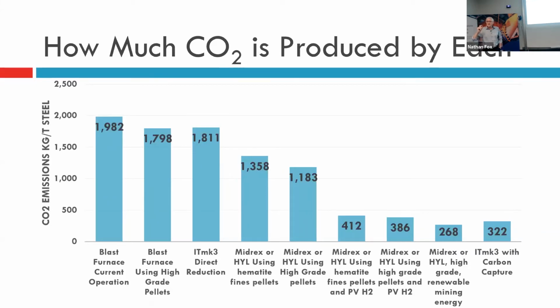If you use the ITmk3 process, where you're mixing carbon with fine iron ore, then it is less than the blast furnace, but it's still a fair bit. If you use the Midrex process, it is quite a bit less than the blast furnace operation. This is the Midrex process if you're using standard 62% iron ore grades. This is the Midrex process if you're using high-grade pellets. So always with high-grade iron ore, you produce less carbon dioxide.